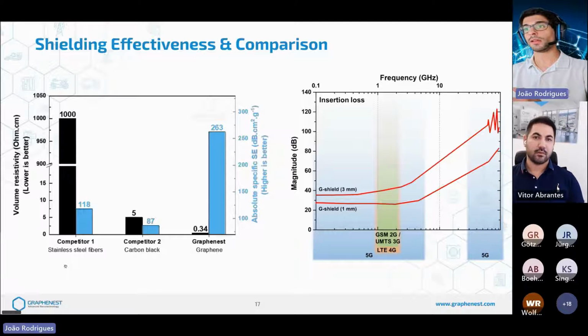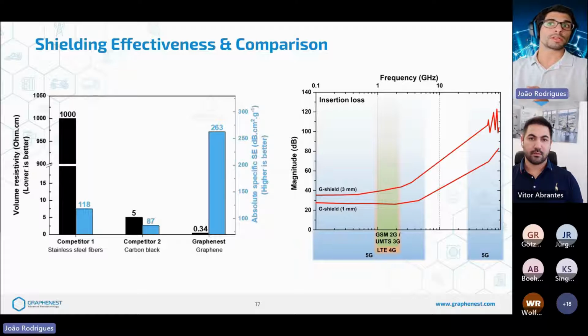And as you can see on the black plot, on the black bars, you have the volume resistivity. For a shielding material, you want the lowest resistivity possible. And as you can see, our product achieved the lowest one. It outperformed both competitors. And this is reflected also in the shielding performance.